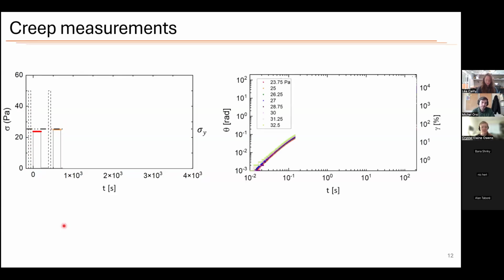The results of the creep show that initially you have an inertial response. This is just part of how the test works. Then you reach a plateau region. Here, this is for stresses that are below the yield stress. There's creep. This is Andrade creep, where you just have a very shallow time dependence where the material is very slowly creeping inside.